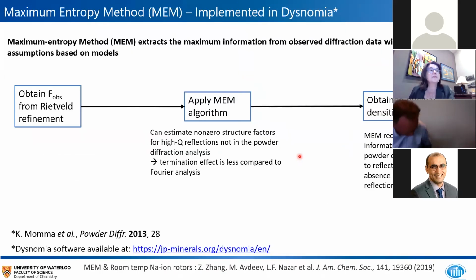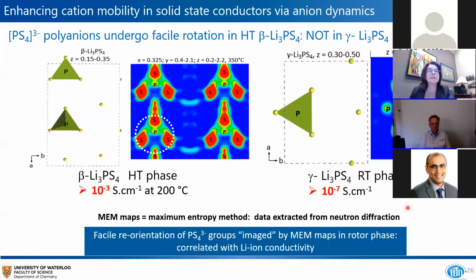Before I explain this, I should just mention what the maximum entropy method is for those of you not familiar with it. It's implemented in a software package called Dysnomia. Effectively you obtain structure factors from a Rietveld refinement. You apply this MEM algorithm, and this allows you to estimate non-zero structure factors. This is just a little aside for any crystallographer in the audience. This allows us then to obtain nuclear densities, and it actually recovers structural information that you often lose in powder diffraction. So you end up getting what we call maximum entropy method maps, and they're actually very powerful.